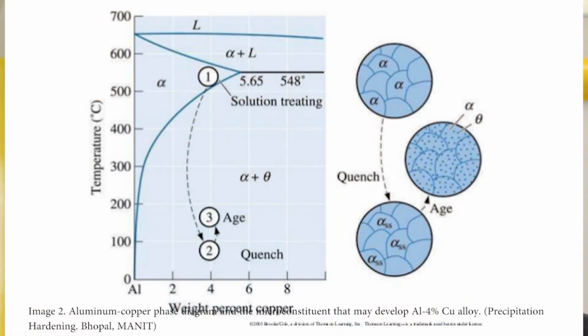Solubilization is when you increase the temperature to increase the percentage of dissolved hardening microconstituents, and that will improve the mechanical properties because you are dissolving all the microconstituents in the best way possible. Well, natural aging occurs when you cool to room temperature, and the big difference between this one and artificial aging is that in artificial aging you increase the temperature to make the process faster and most of the time more efficient. This will increase the mechanical properties in both cases, just that in the natural one you cool at room temperature and it's slower, and the other one is way faster.